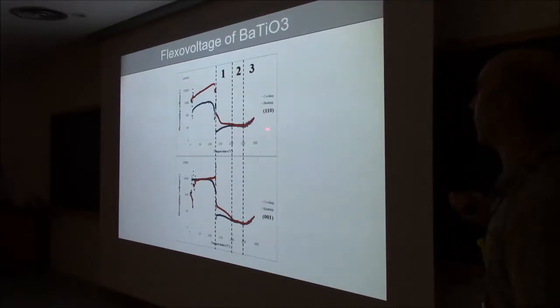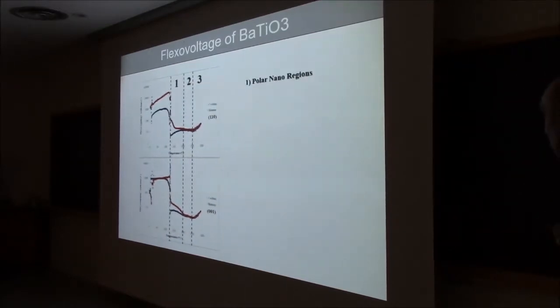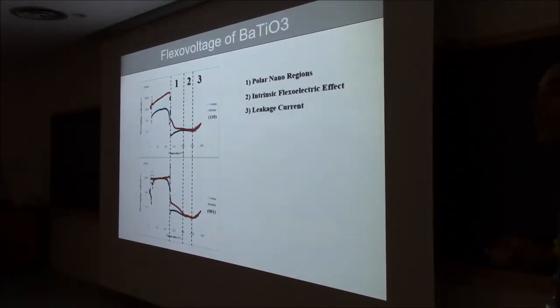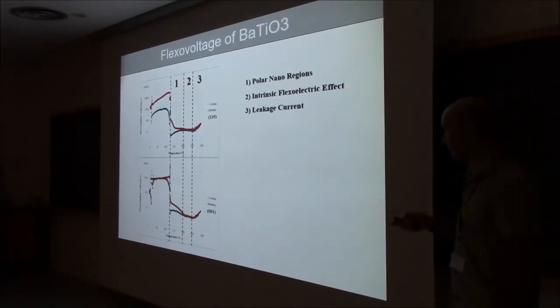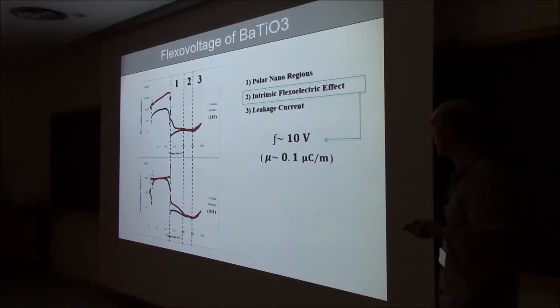Also, you may observe that at very high temperatures, the apparent flexocoupling coefficient starts to go up again. It's no longer flat, it starts to go up. Okay, and we think that this has to do with a free charge contribution. I will get to that later. Okay, but the intrinsic one is of the order of 10 volts.